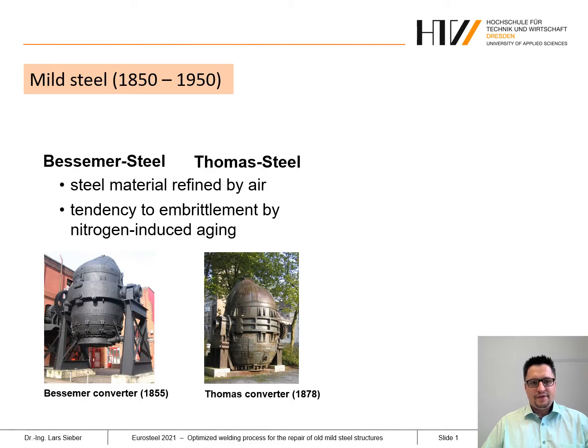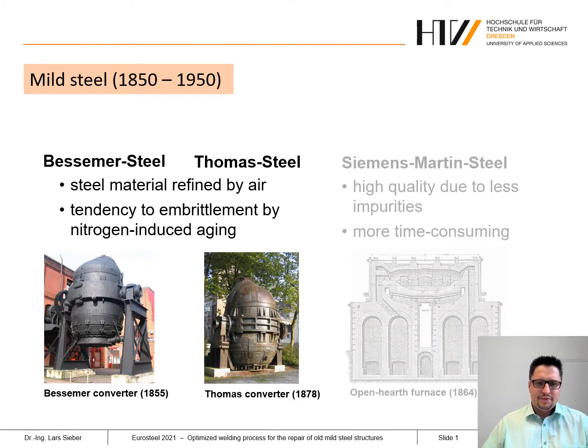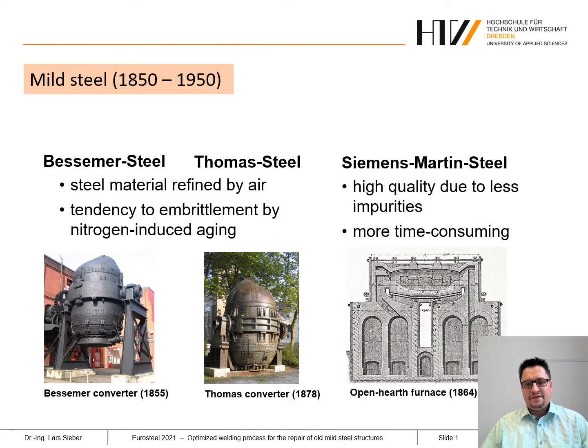The Bessemer steel, together with the Thomas steel, which was widely used in Germany, belongs to the group of the old mild steels refined by air in a converter. Due to the refining by air, a high content of nitrogen was introduced into the material, and this causes a tendency to embrittlement, which we call aging. The second type of old mild steels are the Siemens-Martin steels. These steels were refined in an open hearth furnace, and this process was much more time consuming than the first one, but it was able to produce higher qualities due to fewer impurities.